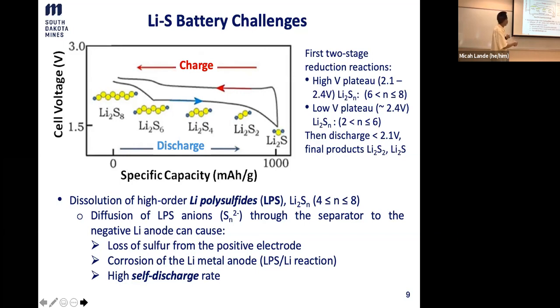So for the sulfur chemistry, when you start, the sulfur combines with lithium to form Li2S8. This is what we call polysulfide. And as you further use your cell phone, it means that you further discharge the cell. The curve follows a little bit of plateau here and a long plateau here, and then it converts to Li2S6. So sulfur is further reduced, right? Then as you keep using your cell phone, it becomes further reduced to S4, and then S2, and lithium sulfide is the final product. You cannot further reduce that, right? So this is the time when your cell phone needs to be recharged. So this is the whole discharge process, and after that you charge the battery back to sulfur. So far so good.